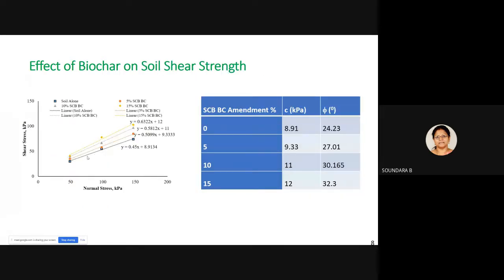These are the values obtained using the direct shear test, the peak shear stress value plotted against the normal stress. We have done tests for three normal stress cases: 50, 100 and 150 kPa, with a strain rate of 1.25 mm per minute. Based on these graphs we have obtained the cohesion and angle of internal friction values for different percentages of biochar mixed soil. The C and phi values are proportionally increased with the increase in the percentage of biochar mixing.